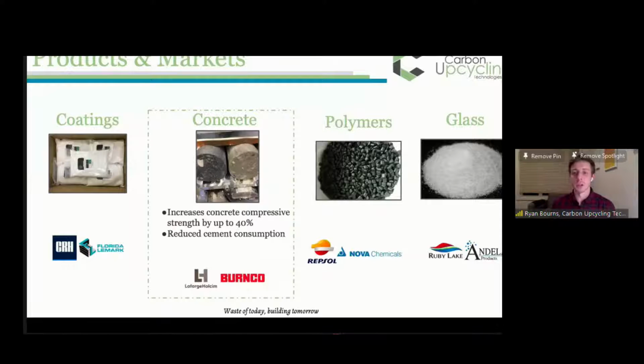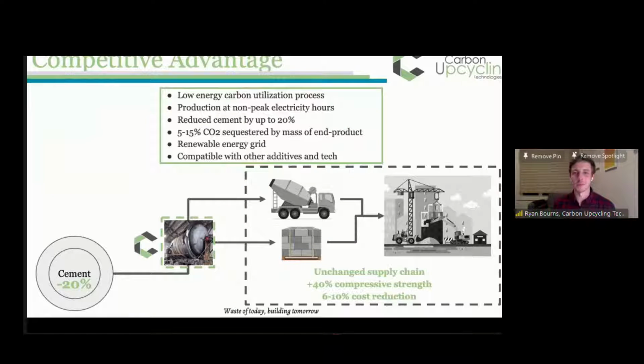So this is something that we've been working on for probably the last 3.5 years, and specifically in the concrete industry. And we've been able to demonstrate that with our process, our enhanced fly ash, as we call it, can increase the compressive strength of concrete by up to 40%. And of course, this means you can further reduce cement and reduce the embodied carbon associated with that material. And this is something that's been validated with partners around the world, like Lafarge Holcim, and more locally to us, a local company called Burnco. You'll see them in a picture later on, probably.